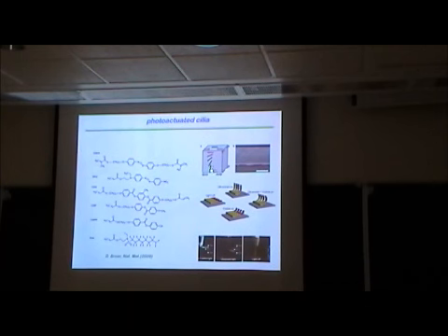The bottom half, where the director is standing up, shrinks in the other direction, which means that in plane it expands. So the top half shrinks, the bottom half expands, and so it bends. He makes, by nano or microfabrication, these little fingers, and you shine light on them, and the fingers bend up.